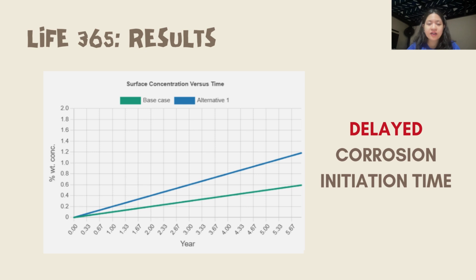Lastly, surface chloride concentrations are shown here. The alternative case exhibits a higher surface concentration than the base case throughout the time frame. This could be due to increased chloride binding or surface accumulation in the model, but importantly, it does not translate to deeper penetration. The internal resistance provided by SCMs offsets this higher surface load, resulting in a much longer corrosion-free period.